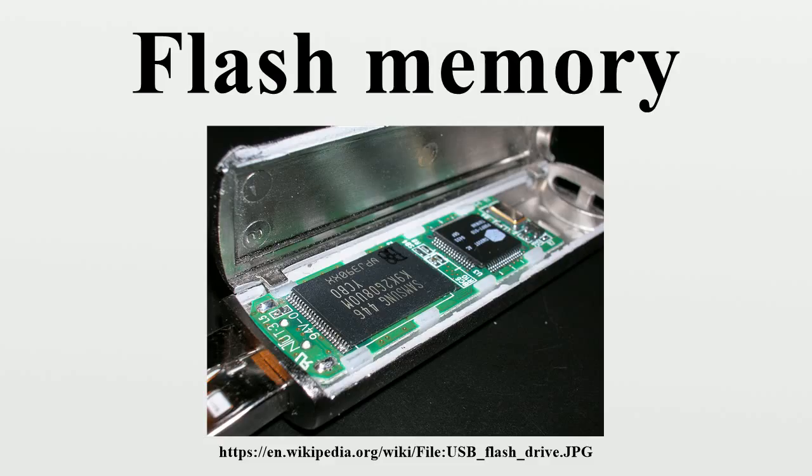In December 2012, Taiwanese engineers from Macronix revealed their intention to announce at the 2012 IEEE International Electron Devices Meeting that they had figured out how to improve NAND flash storage read-write cycles from 10,000 to 100 million cycles using a self-healing process that uses a flash chip with onboard heaters that could anneal small groups of memory cells. The built-in thermal annealing replaces the usual erase cycle with a local high-temperature process that not only erases the stored charge, but also repairs the electron-induced stress in the chip, giving write cycles of at least 100 million.